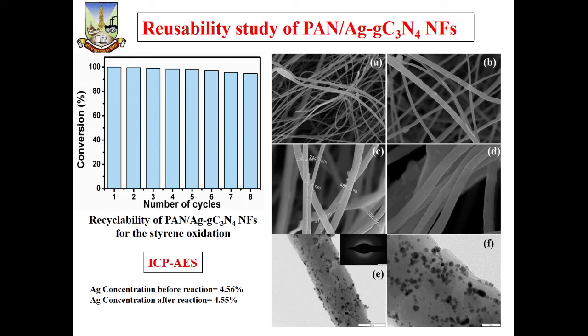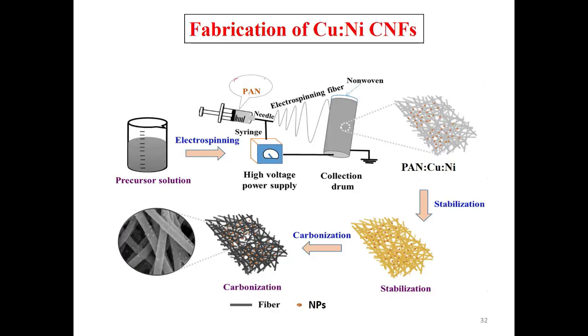Only a few milligrams of that particular silver grafted carbon nitride nanoparticles are removed from the surface, but the maximum amount of nanoparticles adhere to the surface very effectively. And when we did the ICP-AES study, the Ag concentration before reaction was 4.56%, but the Ag concentration after the reaction remains the same, that is 4.55%. Means only a marginal change in the concentration was observed.